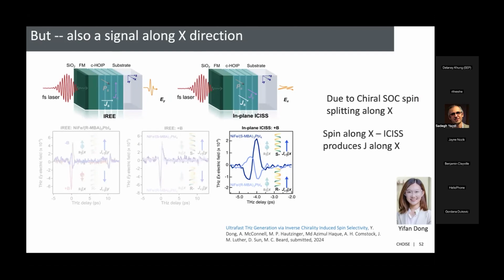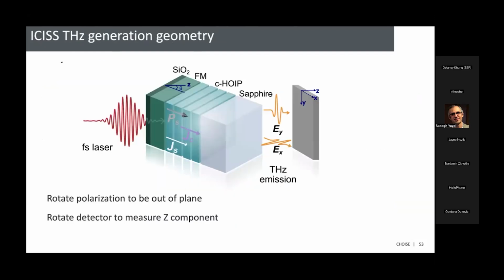Okay, and that's this chiral spin orbit coupling on the X direction. So to measure the out of plane, we have to tilt the sample a little bit so we can measure this, because remember that if you're looking at an antenna that's going like this, you look over here, you can't look directly down the antenna's axis, so you have to turn it a little bit, and then you can measure X and Y.